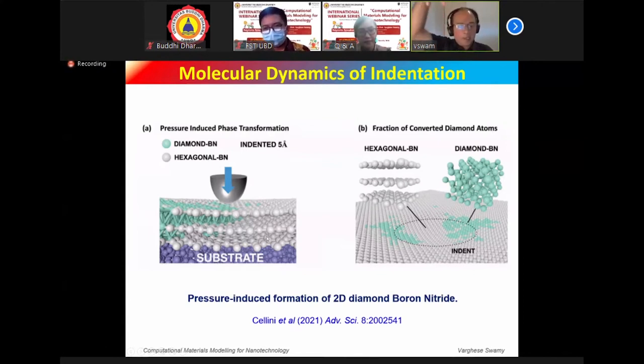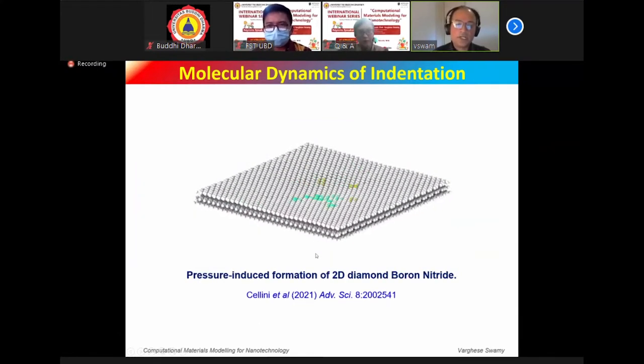So as they bring the indenter onto the material in this simulation, you can see that some green patches forming. That means that there is interlayer bonding happening. So when you look at the h-BN, the bonding is largely what is called the SP2 bonding, which is essentially in-plane, covalent bonding. But when you put two of these layers together and press, some of the SP2 bonding, the in-plane bonding, is converted to SP3 bonding. That means there is bonding happening in between the layers. And that's what is shown here in this movie.